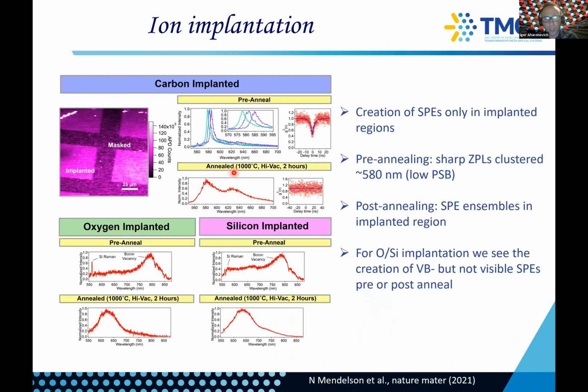And so you can, in a way, repeat it by ion implantation. You can implant different regions, masked and unmasked, and compare carbon implanted. You can see here after annealing you see basically the same signature, and before annealing you would see rather narrow lines as expected. You can repeat it with oxygen and silicon and not see exactly the same features. So this is very convincing, and carbon does indeed play a role.